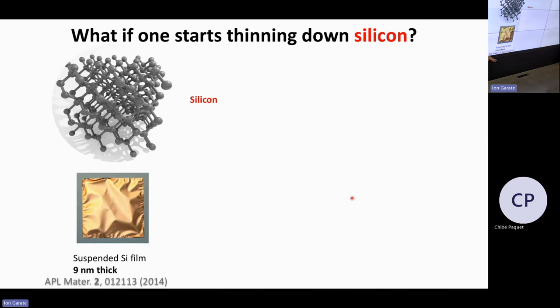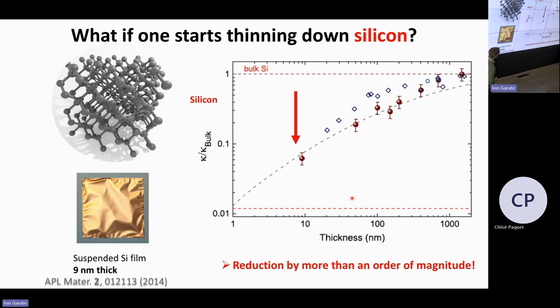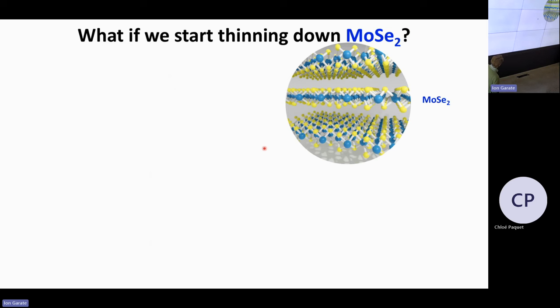Now, what happens if you start thinning down these materials? So this is the case of silicon. As soon as you start thinning down silicon, the thermal conductivity drops by more than an order of magnitude. You get all kinds of problems of interactions with the interface and the surface that make your thermal transport much, much less efficient. And that could be a problem if you want to make transistors with very thin silicon or flexible transistors, for example. Now, what if we start thinning down MoSe2?